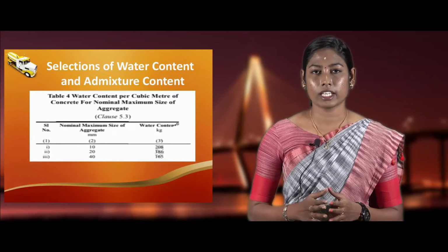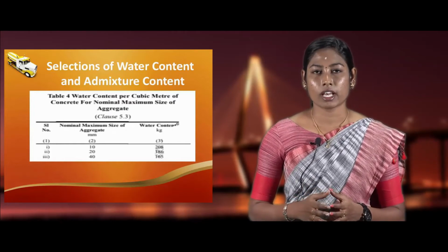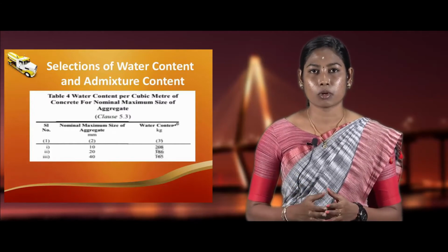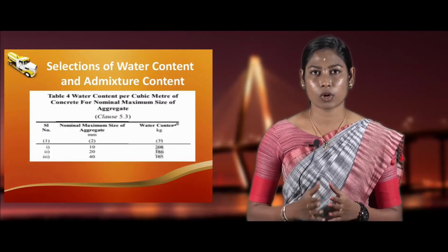On the other hand, an increase in cement content, water cement ratio, temperature and aggregate angularity, and in the proportion of coarse aggregate to fine aggregate, will increase the water demand.